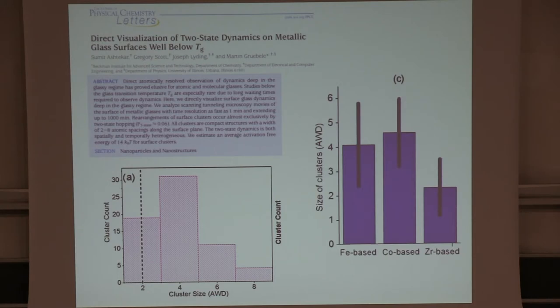And I said, yeah, why don't you measure this, take a sample of metallic glass, measure what the surface looks like, measure what size clusters move around. And I can show you a movie of that, but I don't have the time. But it'll be on the website when we do this. And then this shows you the atomic size of the clusters, which he's able to find in one metallic glass. And you can see they're somewhere in this range, around between 4 and 6. There's something a little perhaps odd going on with zirconium, I don't know.